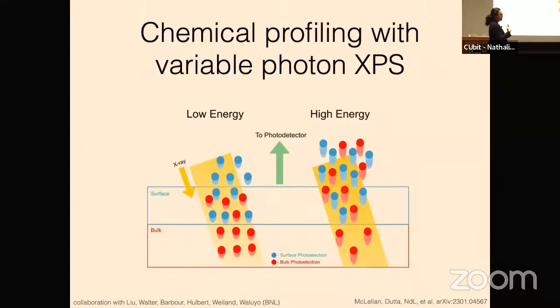But now, so we've done a very systematic job of measuring a lot of tantalum resonators, so now we can go back and say what is actually going on with these oxides. And the method that we came up with to look at this is to look at chemical profiling with X-ray photoelectron spectroscopy. And the general idea is that if you go to a synchrotron, you can change the energy of the incident X-rays. And for very low energies, you're mostly probing the surface because the bulk electrons don't have enough energy to get out. And then at high energies, you're changing the proportion of the surface to the bulk. So by scanning the energy, you can generate a profile of what's going on in depth.